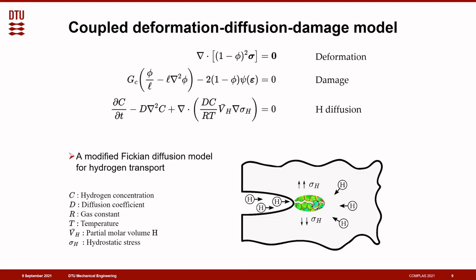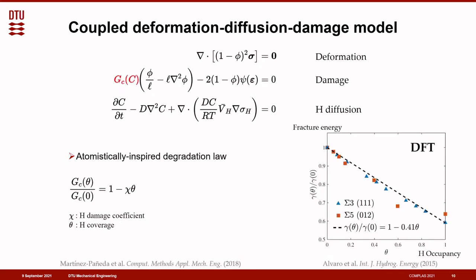So first of all, we model hydrogen transport based on an extension of Fick's law of mass diffusion, basically the third equation, in which hydrogen diffusion is partially driven by the gradients of hydrostatic stress. In addition, we made the toughness of the material depend on the hydrogen concentration, as we see in experiments. The question is, of course, how to define that dependency.